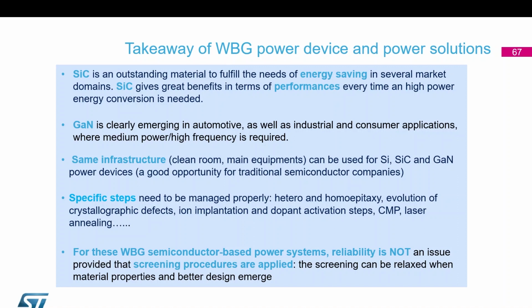One thing from a semiconductor guy is that when you want to move one fab from making silicon power devices to silicon carbide or gallium nitride, you don't need to change everything. Because most of the process, I would say 85% of the process in silicon carbide and probably 90% of the process in gallium nitride, you can do with existing equipment and the existing environment. Of course, you need to invest in those which are, let's say, the distinguishing features of silicon carbide. Silicon carbide is the ion implantation, the high temperature annealing, the epitaxy, and of course the substrate growth if you want to be integrated vertically.